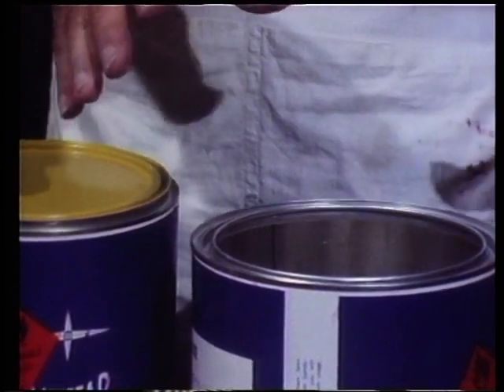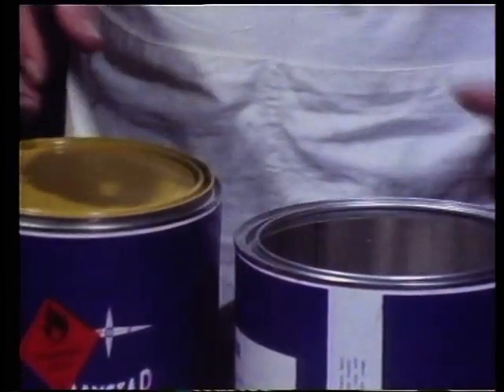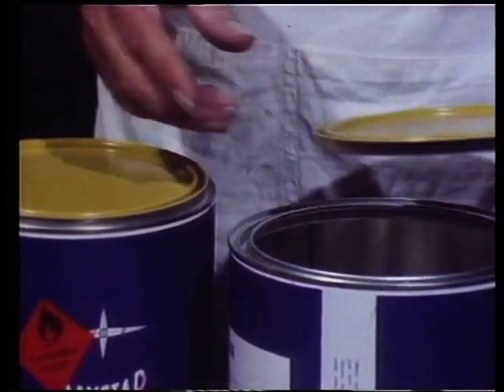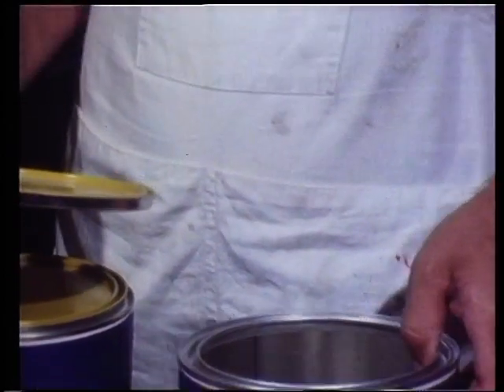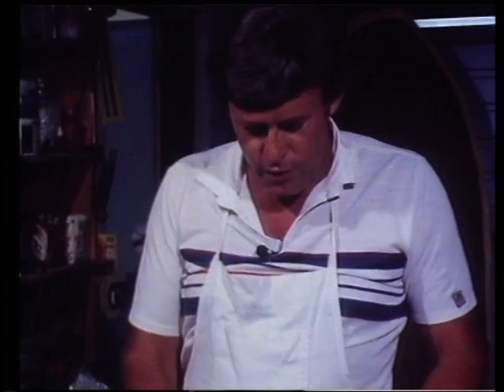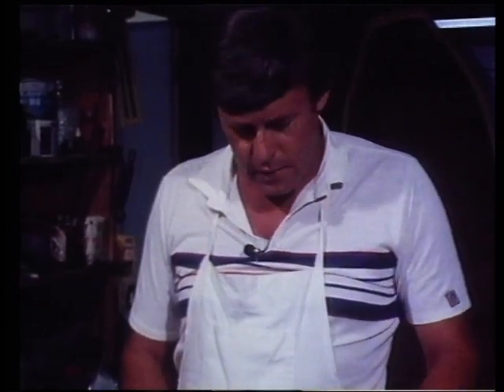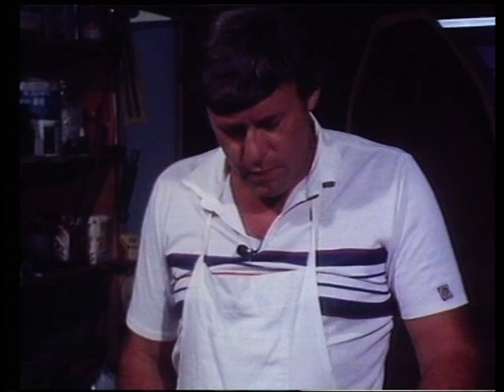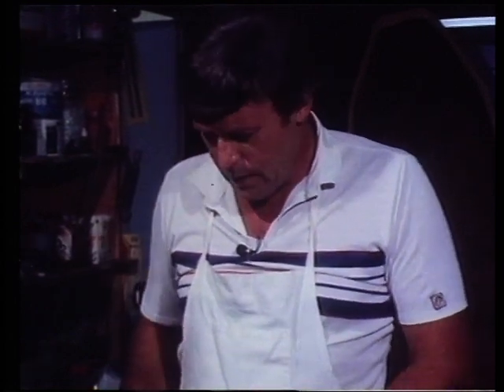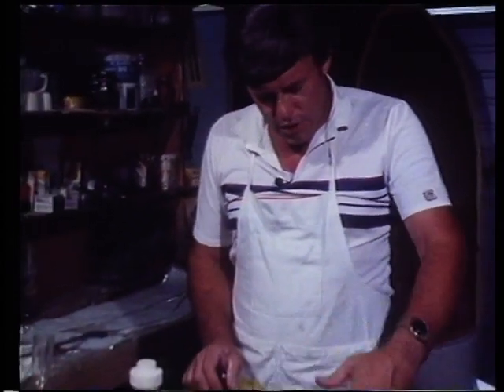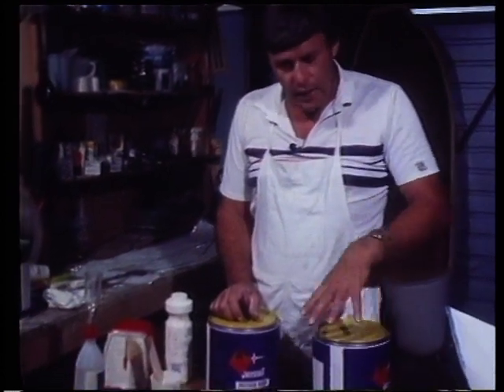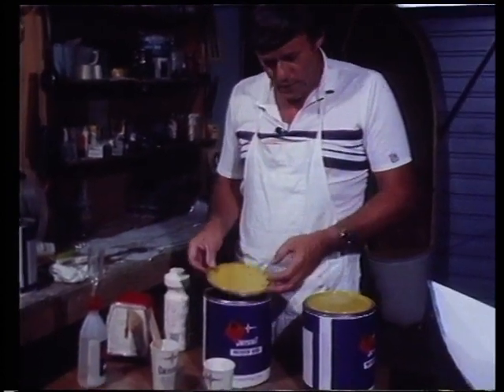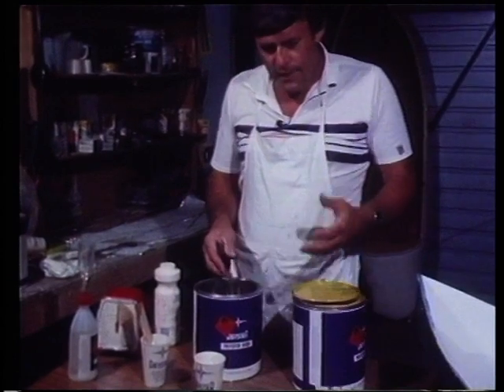Now you leave it in the acetone there. Acetone is a fairly common material, but it has a couple of properties which you should know about and which are most important. Firstly, it evaporates very, very quickly and it's expensive. So make sure that you have a couple of cans with acetone in them with caps on them so that you can minimise the acetone loss. Secondly, when you've washed your brushes in a can of acetone, it leaves a residue of the resin or the gel coat in the acetone, and that makes it very sticky.